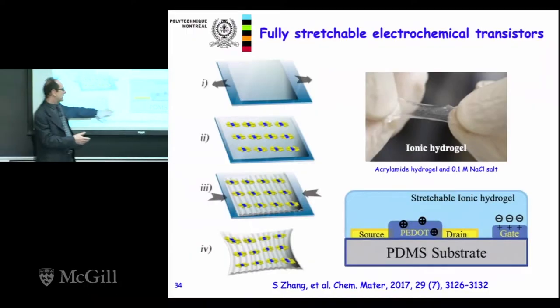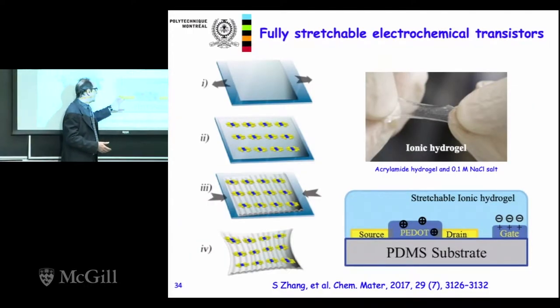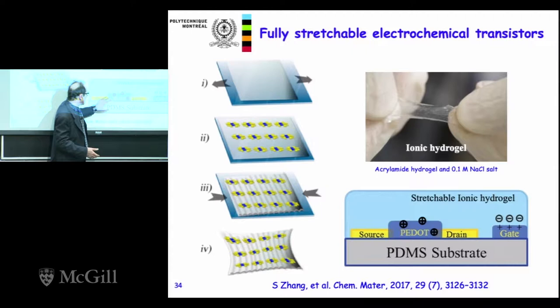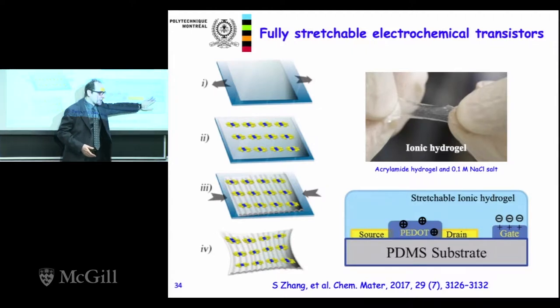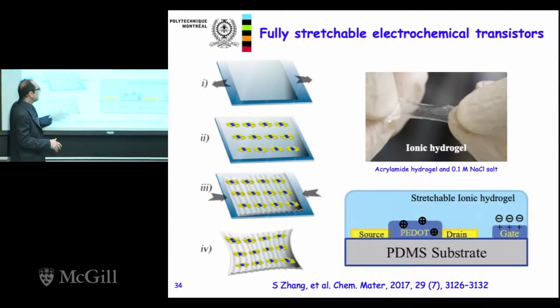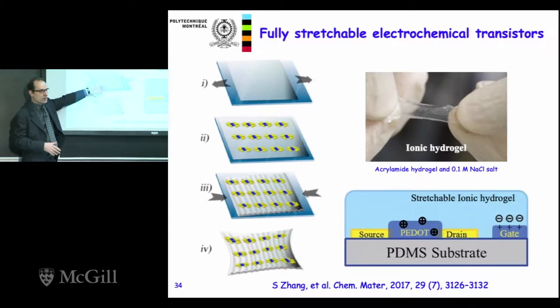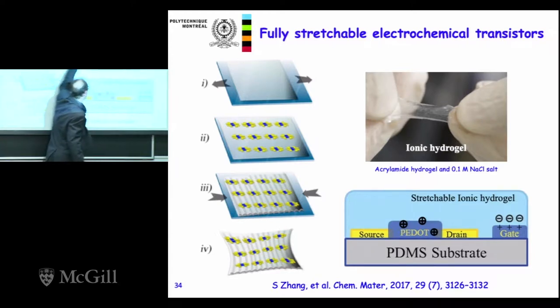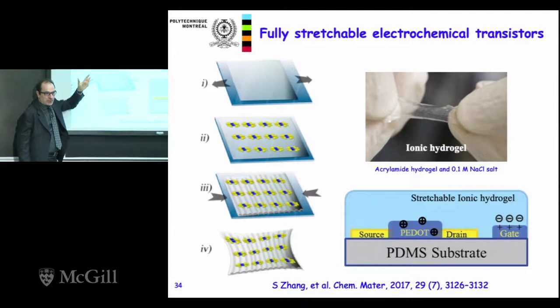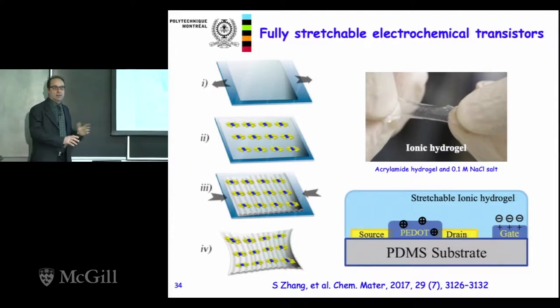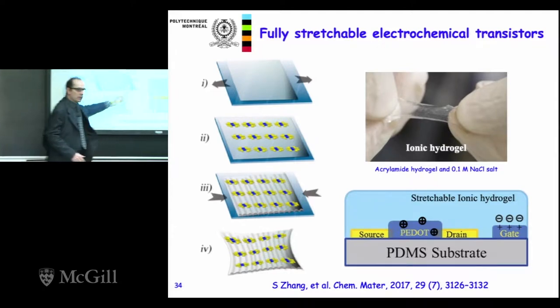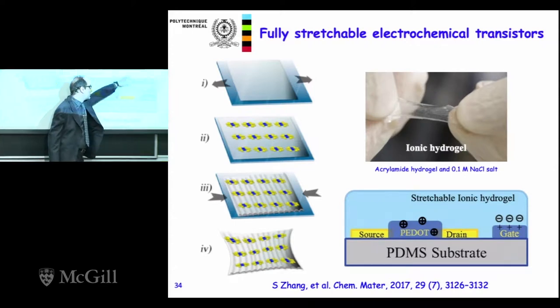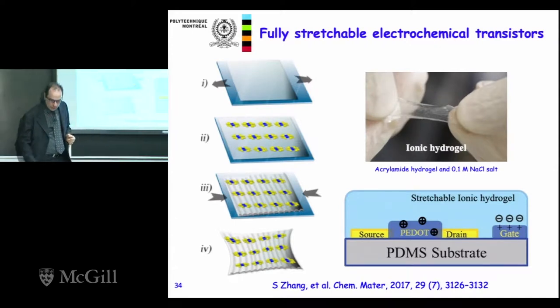So we did that by applying the buckling method to make the metal and the conducting polymer. We have, this time, the gate, which is a planar one. And we added a stretchable hydrogel as the electrolyte. This is how it looks. It's based on a kind of conventional acrylamide chemistry. We just modified the process a little bit. We used NaCl instead of lithium, just because it's much cheaper.